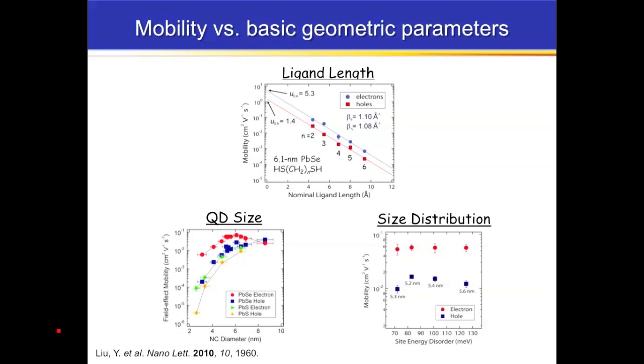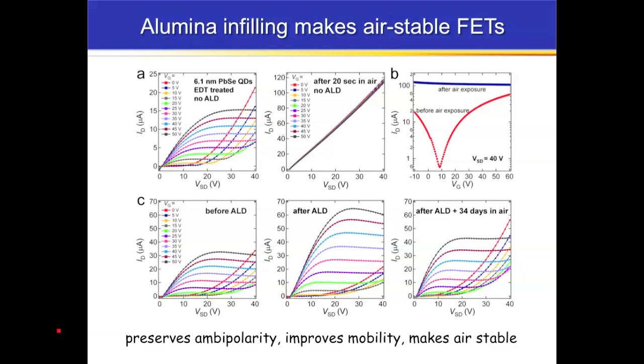very strong, and the size distribution has a surprisingly flat dependence. We can explain both of these in terms of trap states or recombination centers within the band gap of the quantum dots, but I don't really have time to talk about that. So we use these field effect transistors.